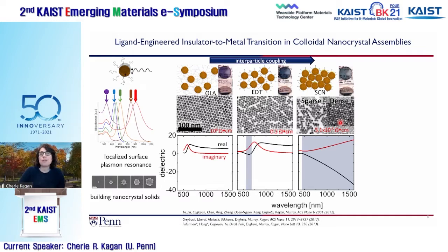If you look at the dielectric function, what you see now is that if you follow the real part of the dielectric function, it's everywhere negative. And that's characteristic of a true metal. And the idea is that by simple ligand exchange, which we carry out at room temperature, we can really take these insulating materials and make them into highly conductive metals, both at DC and optical frequencies.